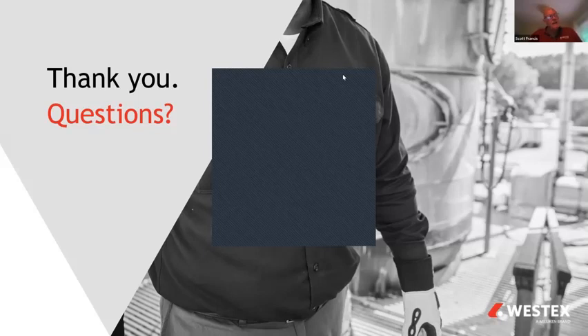For your cotton-rich fabrics, repeated use of chlorine bleach will break down the polymer that's in the core of the cotton fiber. So you want to avoid chlorine bleach. Most of these are colored garments, so they're not white, right? We usually discourage people from using white flame resistant garments because they might be tempted to bleach it.